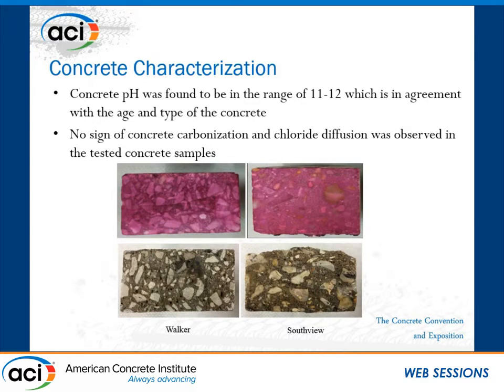After the GFRP were taken out from the cores, before characterizing the GFRP itself, first we provide a general characterization of the concrete itself to show what has happened to the concrete after 12 and 17 years of service for these 2 bridges. First, the pH of the concrete was found to be in the range of 11 to 12, which is an expected range for the type and age of the concrete.